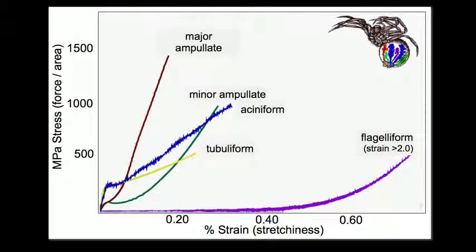Here are stress-strain curves generated by tensile testing five fibers made by the same spider. The five fibers have different behaviors. Looking at the vertical axis — stress — if you look at the maximum stress value for each fiber, there's a lot of variation. In fact, drag line or major ampullate silk is the strongest of these fibers. We think that's because the drag line silk, used to make the frame and radii for a web, needs to be very strong.